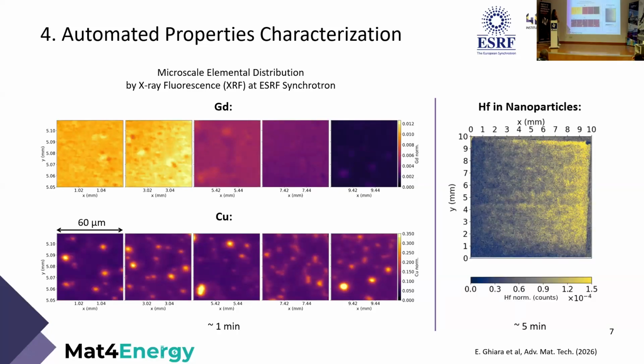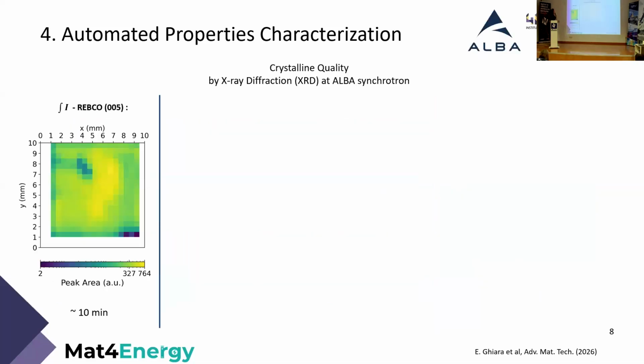At the same beamline, with the same strategy, we were also able to detect the hafnium concentration in a nanocomposite sample, which is directly correlated with the nanoparticle concentration. And this was really tricky to achieve since the atomic percentage of hafnium is really little in the sample. So this verifies the fact that we can also produce a combinatorial nanocomposite gradient.